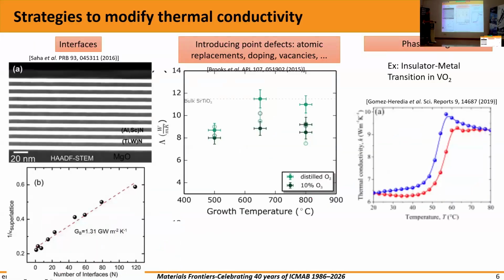And then the question is how to modify the thermal conductivity in a solid state material. Basically, we have three main ways to do it. One is interfaces scattering phonons. If you put more and more interfaces, or the density of interfaces is larger, then you're going to reduce the thermal conductivity just because you're going to have more phonon scattering centers.